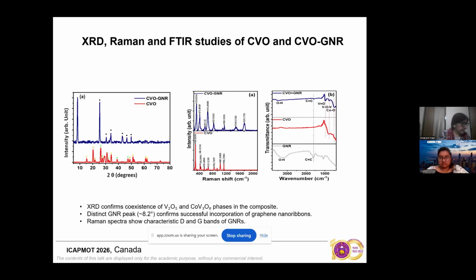Looking at the XRD, the graphene nanoribbons have a typical peak at around 2 theta of 8.2 degrees, which is a characteristic peak of the GNRs, and then the peak at 26.8 degrees down here. This is the typical 002 plane, which is observed in the XRD spectra of both CVO as well as GNR. This peak is present in the composite also, so whatever the characteristics of CVO and of GNR, both are present in the CVO GNR composite.